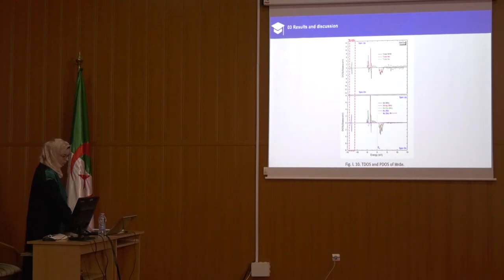The second range, from -5 to near the Fermi level, the density of states for the spin up case comes from the hybridization between 3d Eg and 3d T2g manganese and 4p Se orbitals, where the spin down case is dominated essentially by the 4p Se orbitals.